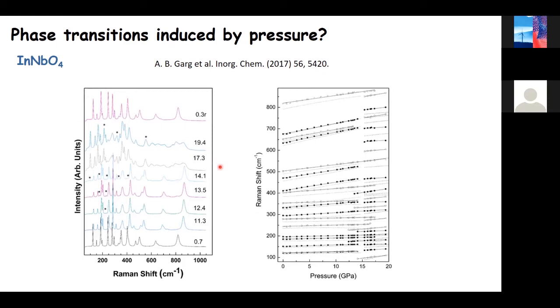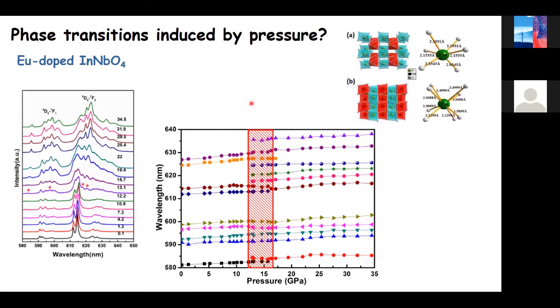I will show now another slide to show that the Raman experiment also confirmed the same phase transition as in indium tantalate, but I would like to focus on the electronic properties. This is just another slide before commenting on the electronic properties. These are luminescence experiments in a compound which has been doped with europium. Europium will substitute indium.